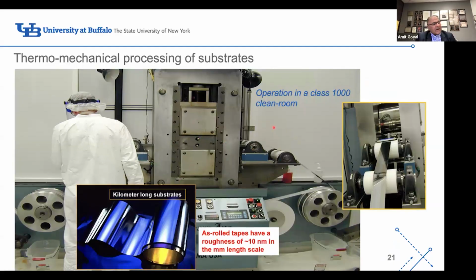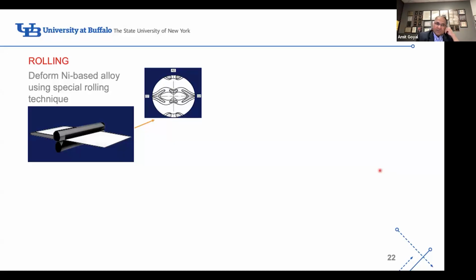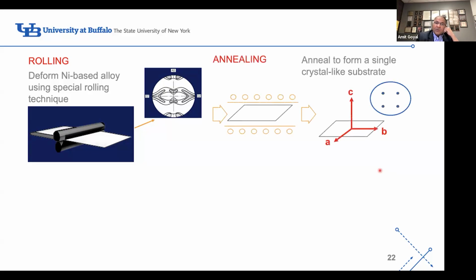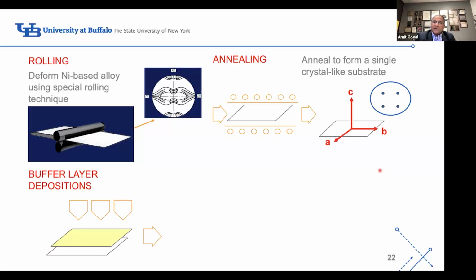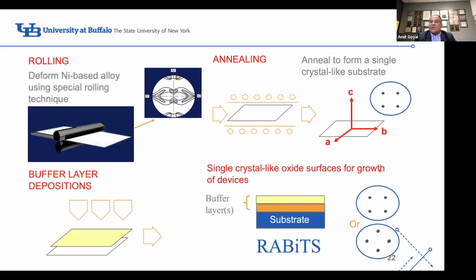The RABiTS process, we first start with rolling a metal tape of a certain composition. It looks something like this. The rolling is done in a class 1000 clean room. As-rolled tapes have a surface finish so that they can take atomic scale deposition of materials. So we start with the metal tape. We roll it to have a certain rolling texture. We then anneal the sheet in a furnace such that when we are done, the 100 plane in the metal is aligned parallel to the surface of the tape, and the 100 direction is aligned along the rolling direction. Then we deposit oxide buffer layers and superconductors on it to have what we call the RABiTS substrate. This is just the buffer layers, and the substrate is what we call RABiTS. And on top of this, we deposit superconductors.